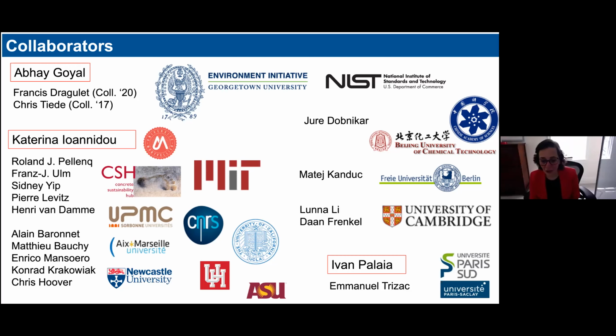Okay, so that's a very good point. In fact, cement doesn't really dry. This is a very important thing because we say cement is drying, but in fact, cement is setting. And water actually doesn't really go away. Of course, there is some drying from the surface, but that's a minimal amount. Most of the water remains in the structure, and it's used to develop those cohesive interactions that I was talking about. And that's the reason why you can make cement and harden cement also underwater, right?